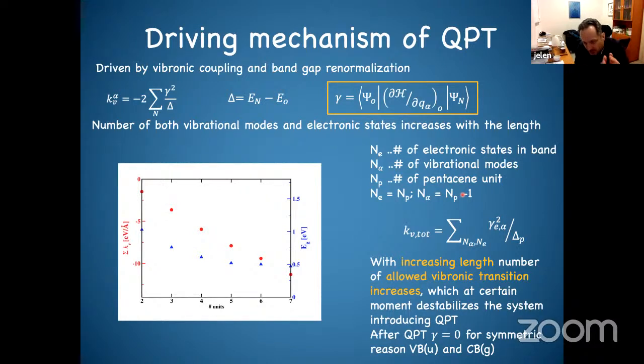But what's more, it is developing new vibrational states which were not observable in the system far away. So close to this phase transition, you also see new vibrational modes which are related to these new states, like a pendulum going from one side to the other. And these states are very coherent. These vibrational states stay for picoseconds.